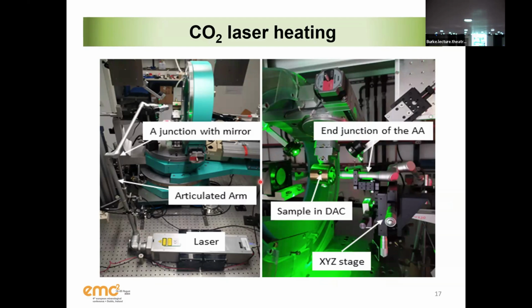So what we have started to do in the last 5 years now, it's a long process and would not be possible without Alex, is to use laser heating of our single crystal and measure velocity at temperature and pressure. There are several problems, but one of them is that your samples are transparent, which means that you have to use a CO2 laser.